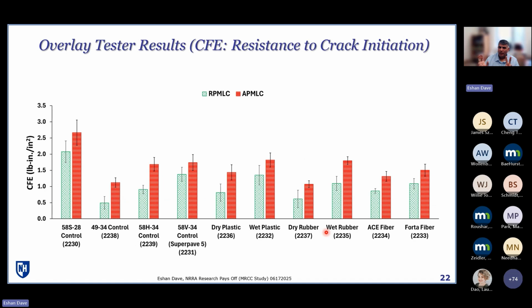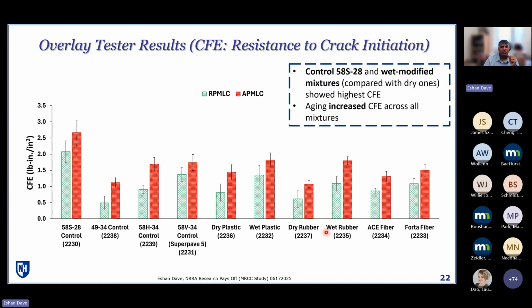Overlay tester. So again, there's two parameters that you can extract from the overlay tester. You have what is called the CFE, which is your resistance to crack initiation. Here you essentially want a higher value in order to have good performance. And unlike all of the other parameters that we saw so far, really the control was the one that had the highest value here, which also makes sense because this parameter is really telling you how much force it takes for that crack to get going. And when you have a stiffer mixture, it gives you a higher value. So we are seeing that aspect here. And that's why with aging, all of these parameters exceeded as compared to their unaged condition.